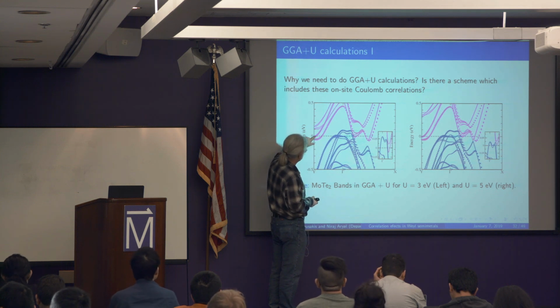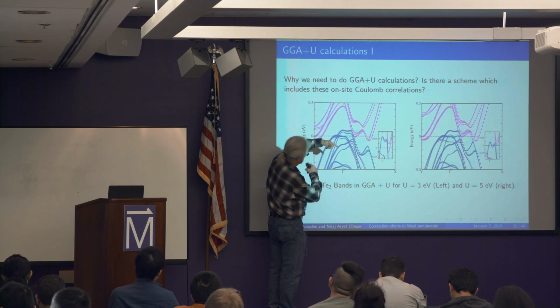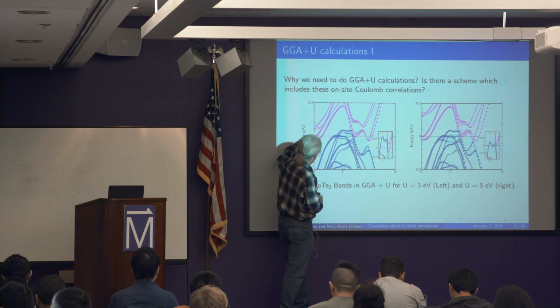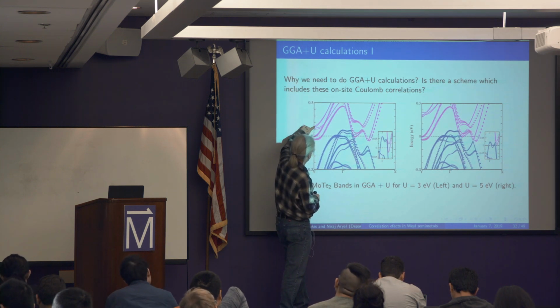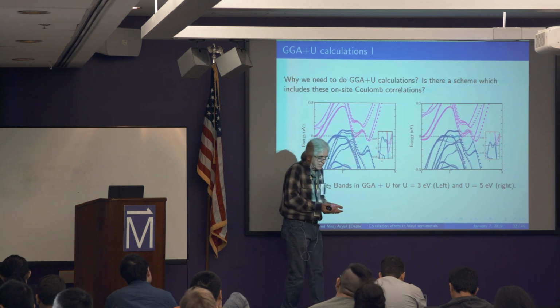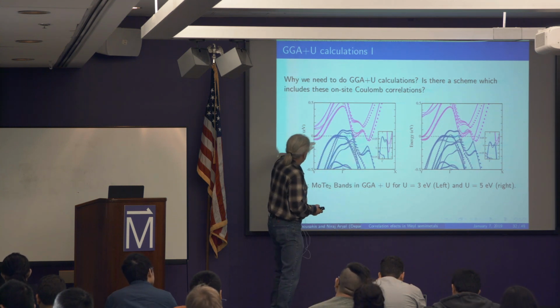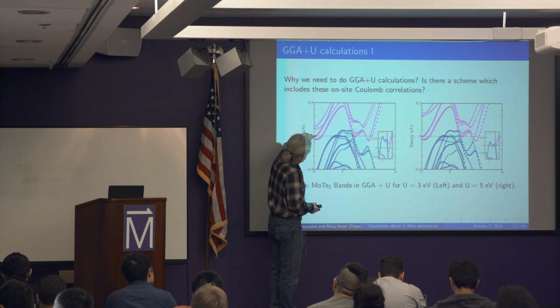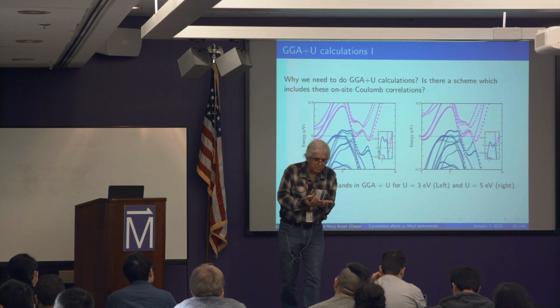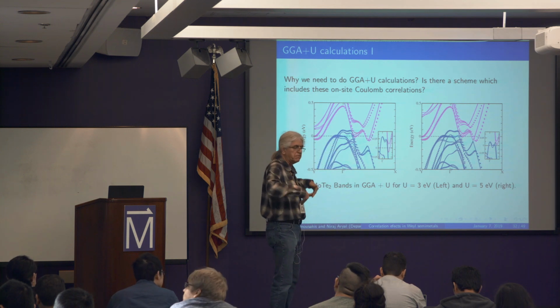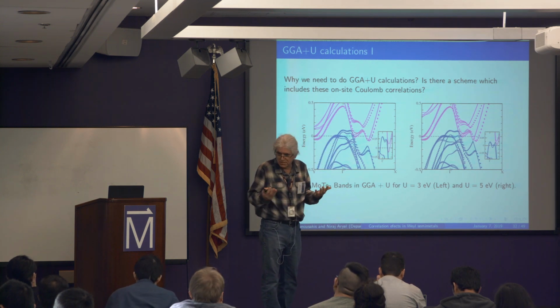So one of the big effects is this pocket which is here, creating electron pockets. Electron pockets just go up because of this Coulomb repulsion. This Coulomb repulsion just moves this up, and the carriers that were here come down because you have to conserve the charge. The electrons that were occupying those states come down and fill the holes, right?